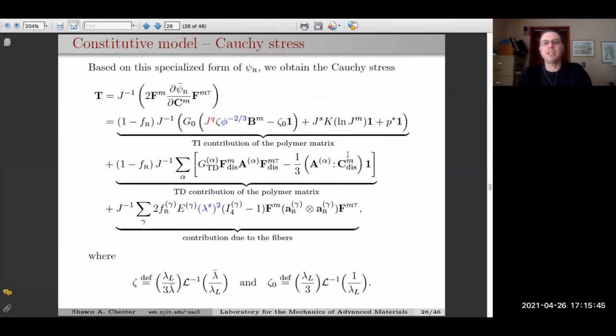And so what you see here in red is that parameter Q that we've added to try and eventually help us get the slope, the modulus in tension. The phi that you see here shows how the degree of swelling affects the apparent modulus. Right? Now, if we have no fluid, this reduces down, and if we have no fibers, it reduces down to plain old hyperelasticity.